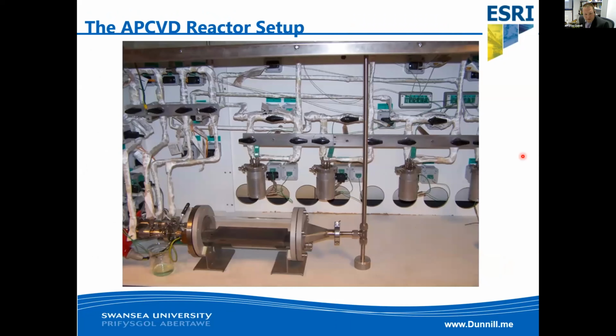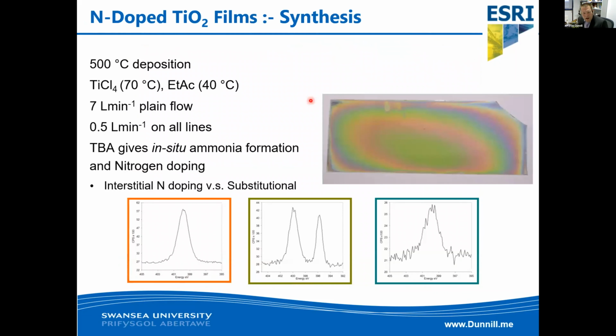So how do we do it? Well, we look at atmospheric pressure chemical vapor deposition. So this is my rig from UCL. You can see at the back, we've got chambers of liquid chemicals and volatile chemicals that we can heat up, changing the vapor pressure. We can pass heated gas through them. We can take all the 4 different feeds down here and onto a heated glass substrate. So we can do chemical vapor deposition down onto the glass. This is an example here where we've got nitrogen doped TiO2 films.